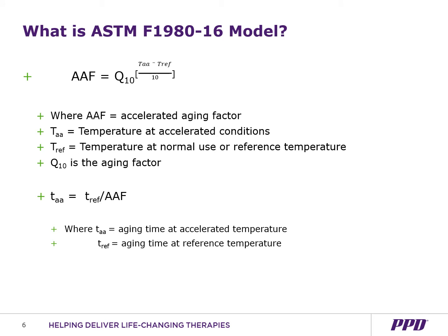So the ASTM model was developed as a guide for accelerated aging of sterile barrier systems for medical device testing. It had previously been proposed as a way to calculate and justify accelerated migration testing for extractables and leachable studies. The technique is based on an accelerated aging factor, or an AAF, and equated that to the accelerated temperature minus the reference temperature, or the normal use temperature, and the Q10 aging factor. That Q10 aging factor we will explore more with some of our empirical data. And then you can relate this to study duration, as shown at the bottom of the slide there, where the aging time at the accelerated temperature is equal to the aging time at the reference temperature divided by that accelerated aging factor. So this then allows us to correlate time and temperature together.